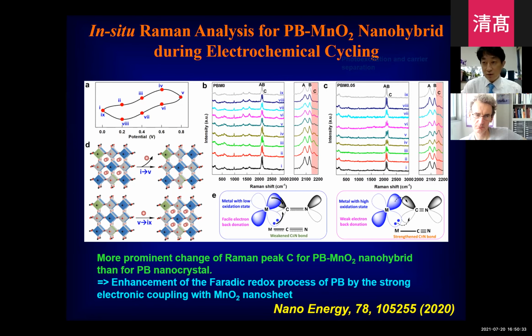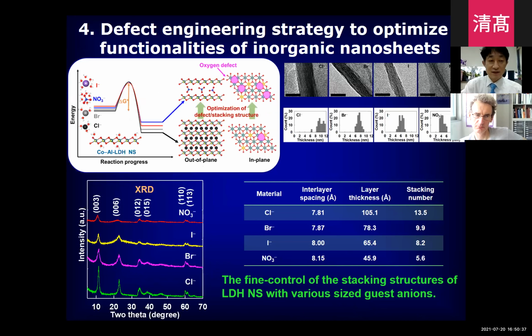Okay, let me move to another topic. We try to control the defect structure of the nanosheet and hybrid. This is one example. We can synthesize the LDH nanosheet and restack it with several representative anionic guest species. There is a significant change in size and charge density. We found that controlling the charge density and size of guest species allows us to control the defect structure and the stacking thickness. So by lowering the charge density of the guest species, we can thin the layer thickness of the restacked nanosheet.